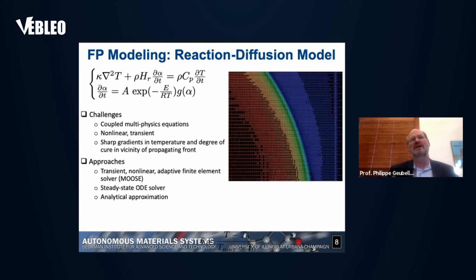I will emphasize the modeling aspect in this presentation, and it's important to realize the basic equation that characterizes this process. It's simply based on the reaction-diffusion model. It's been around for a while. It's written in terms of the temperature and alpha, which is the degree of cure. The degree of cure is 0 when it's a monomer, and 1 when it's a fully polymerized polymer, right? The key quantities you have here are the thermal conductivity and the density. HR is the heat of reaction, so that's the amount of heat that is created by the exothermic reaction, right? You have a term that is proportional to the evolution of the degree of cure, which is itself characterized by the second equation, which is a cure kinetic model. A is the pre-exponential constant, E is the activation energy, and the coefficients that show up in the second equation are typically obtained through an experiment called differential scanning calorimetry.